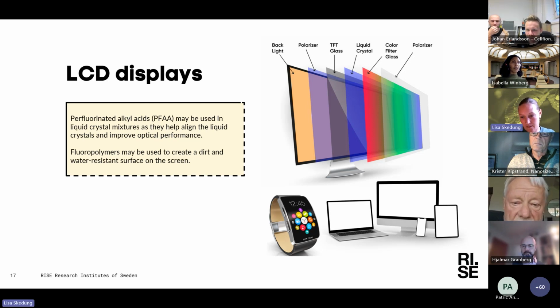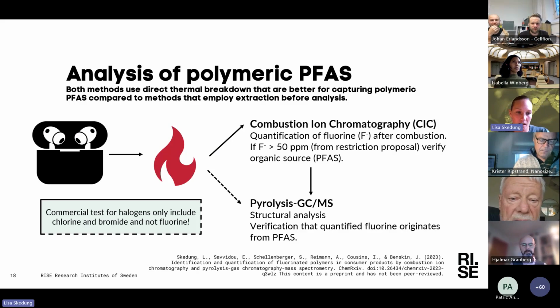I have one last example, but before doing that, I just want to highlight that in the POPFRE project, we worked a lot with PFAS analysis and with methods trying to capture polymeric PFAS. And here we use a combination of quantification of total fluorine with combustion ion chromatography, and then if we measure more than 50 parts per million, if you remember from the restriction proposal, then we can verify if the source of fluorine is actually PFAS. So then with pyrolysis GCMS, we can get more structural information and verify that the fluorine comes from PFAS.